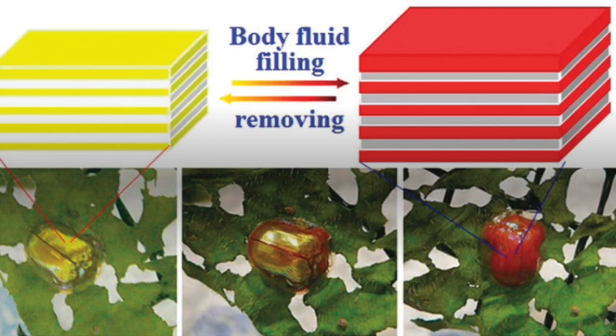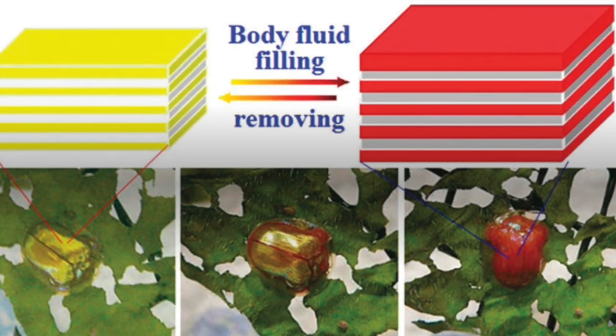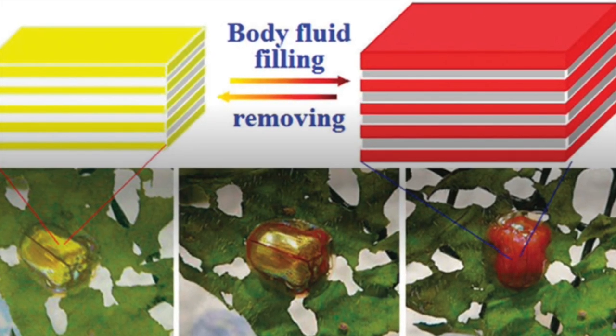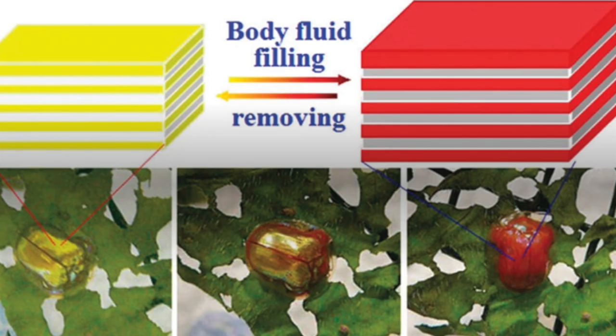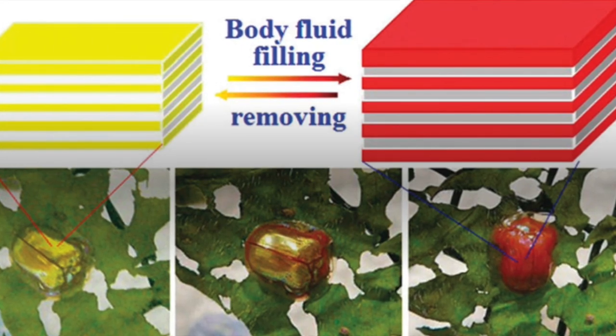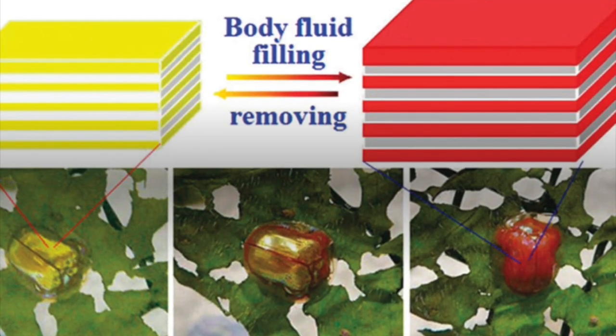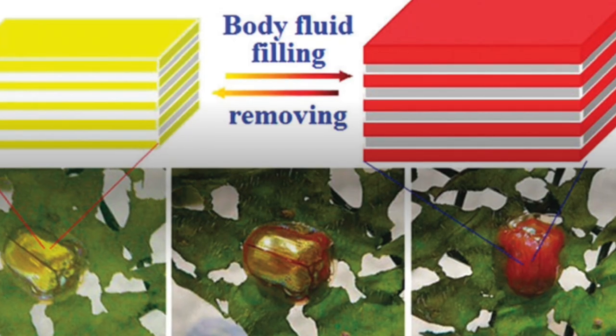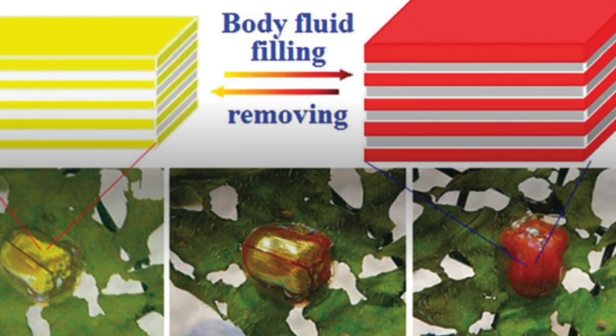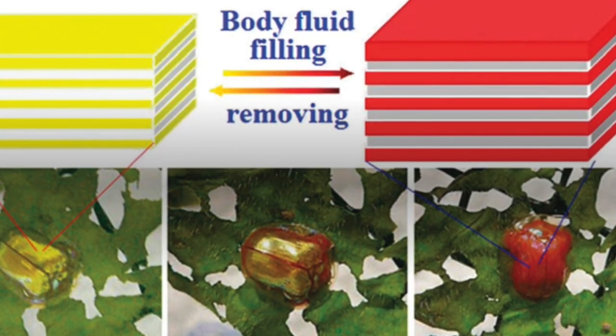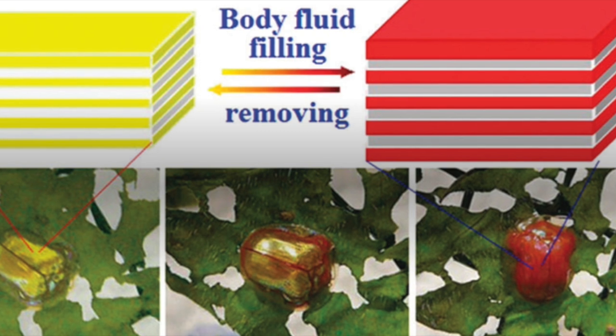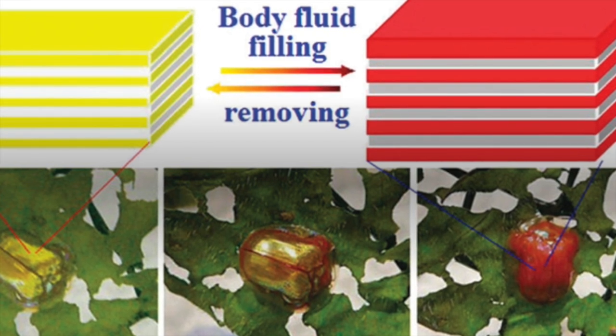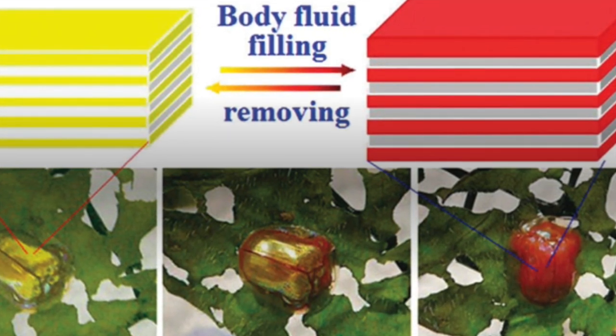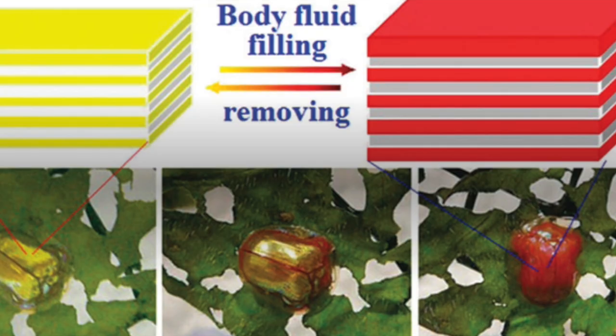Charidotella egregia, the golden tortoise beetle, reversibly alters its cuticle from metallic gold to a dull orange-red when stressed, using a moisture-dependent structural mechanism. The gold color, produced by a chirped multilayer reflector, a Bragg mirror, in the cuticle that reflects light via interference, is lost when the beetle expels water, transforming the structure into a translucent scattering layer.